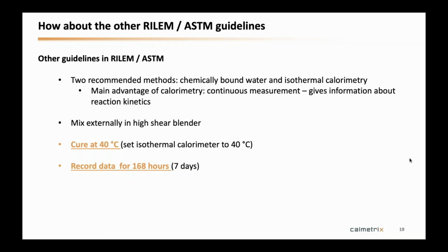Especially the water has a high heat capacity, so it's quite okay. But when you have the calorimeter at 40 and your ambient temperature is 20, or the calorimeter at 60 and your ambient temperature is at 20, very quickly even if you preheat the materials, they go from 40 to 37, and this is it. And then you get this negative peak, because calorimeters are sensitive; they measure that difference very well, and it takes some time to recover. So preheating works well when you mix externally, when the temperature gradient between the calorimeter and your ambient temperature where you mix is not very large, right? The larger it is, the more iffy it gets.